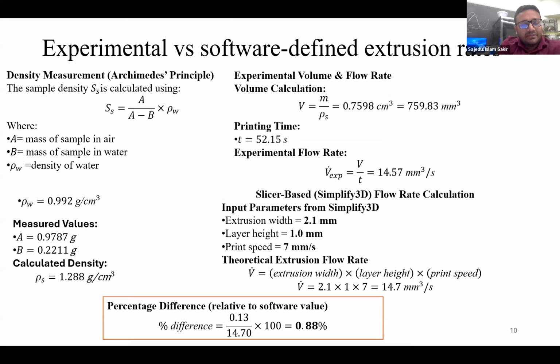So what I have done here is use density measurement by the Archimedes principle. Based on this formula, A is the sample that I have printed. I take the mass in the air, then take the sample to the water for measuring the density based on the water density. This is the water density we are using in this formula. So the part I have printed, I measure it in the air in the measurement device, and I got 0.9787, and then in the water it's 0.2211 gram, all in grams. Then from this formula I got the density of the sample as 1.288 gram per centimeter cube. So this is actually the density of the material.